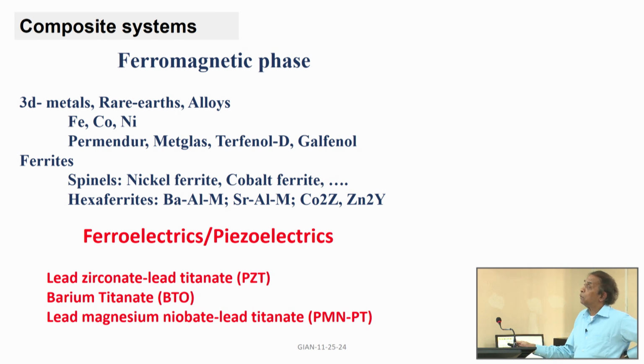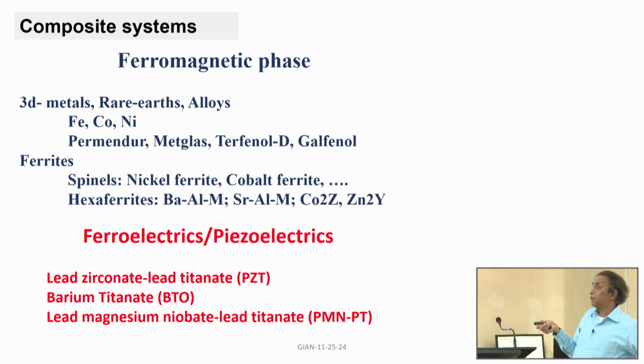And also one could use ferrites. Ferrites are ferrimagnetic, as I mentioned earlier. The magnetic ordering is antiparallel with two different magnetic moments which are not equal. So, there is a net magnetic moment, it behaves like a ferromagnet, and we will talk about ferrites with cubic structure, these are spinel ferrites, and there are quite a few of them: nickel ferrite, cobalt ferrite, nickel zinc, cobalt zinc, and so on.